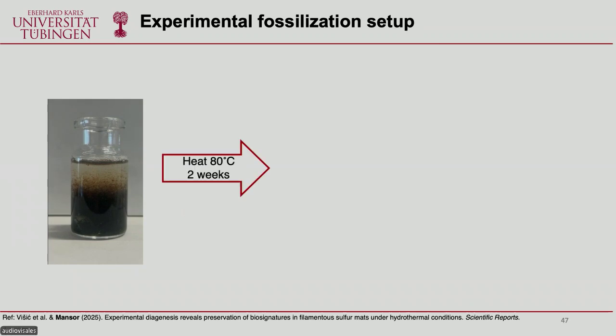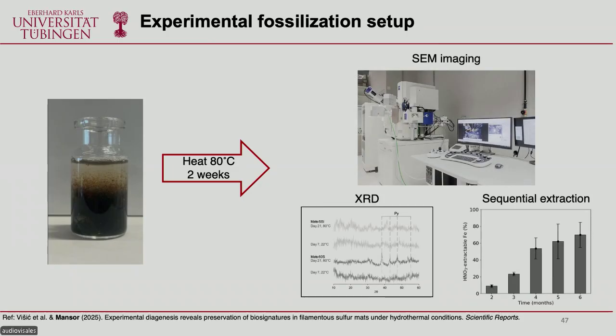And then we put this at high temperature, incubating them at 80 degrees Celsius for 2 weeks. And we use a variety of techniques in order to identify their mineralogy and to look at the cell-mineral association, using SEM, X-ray diffraction, and sequential extraction.